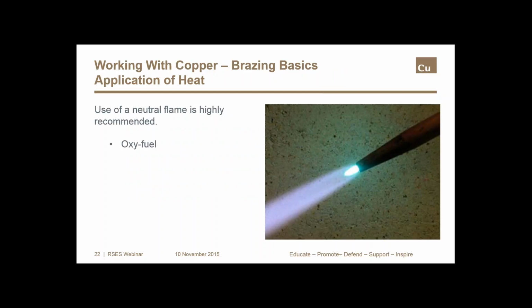We want to apply heat to the parts to be joined with an oxy-fuel or an air-fuel torch. The photo on this slide shows an oxy-fuel torch. You want to adjust the oxygen flow to a neutral flame. A neutral flame has a minimal glow near the nozzle, as the photo shows. The Copper Development Association recommends avoiding a carburizing flame because of the excessive amounts of carbon that this flame introduces into the joint. Excessive oxygen is also a problem, and this flame is referred to as an oxidizing flame. Needless to say, an oxidizing flame should not be used for brazing.